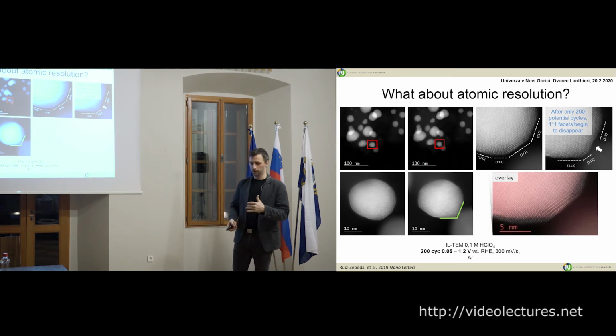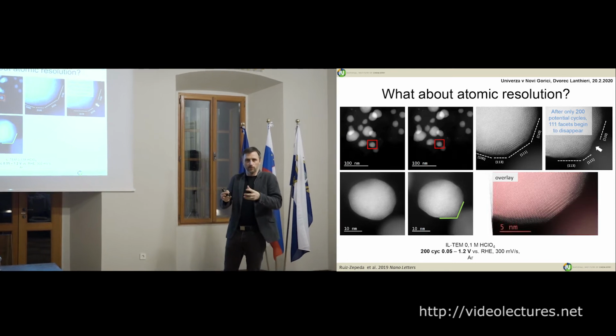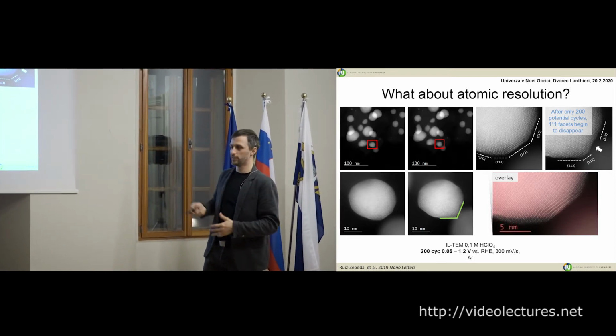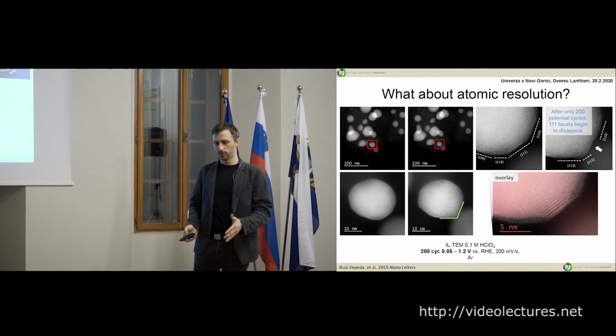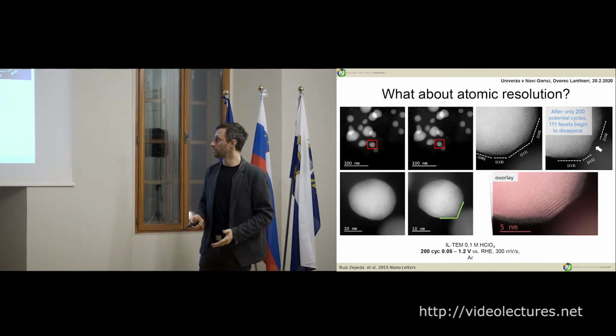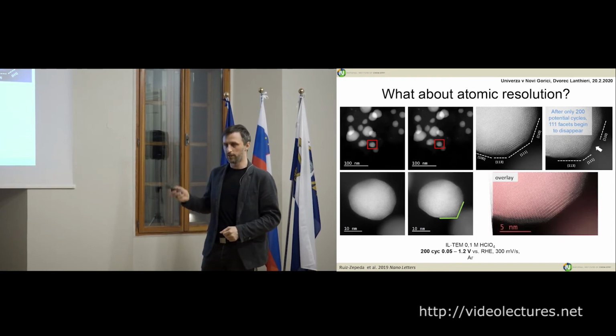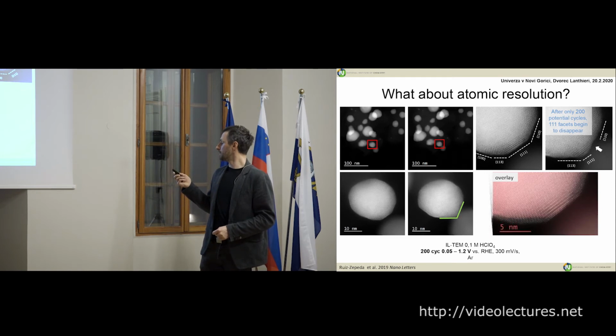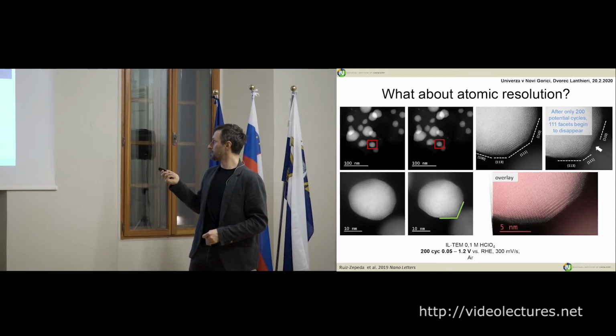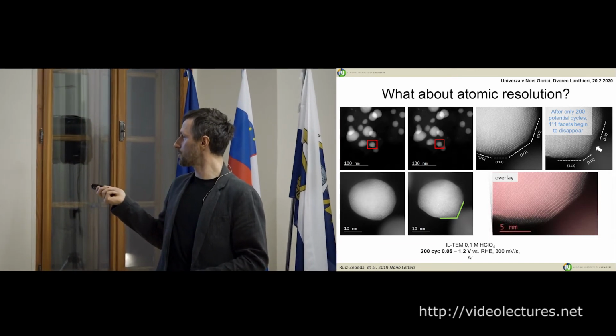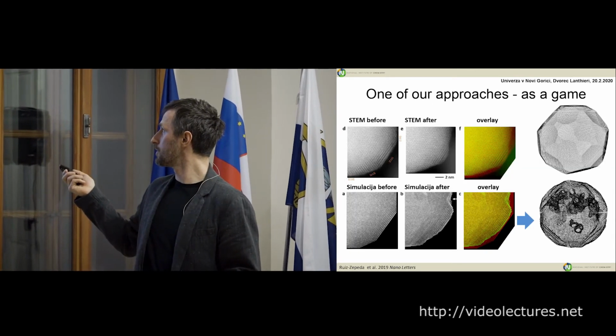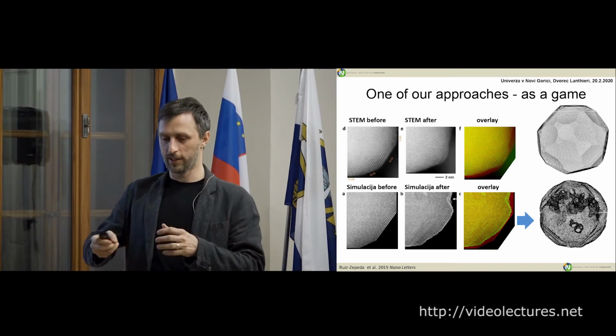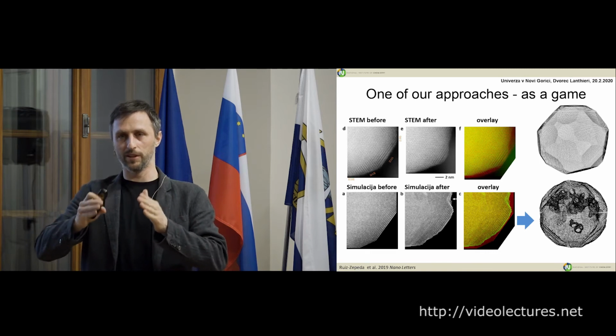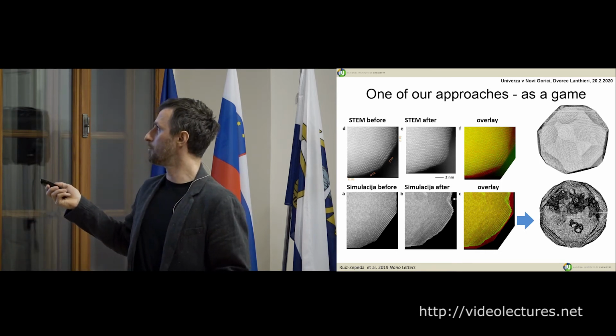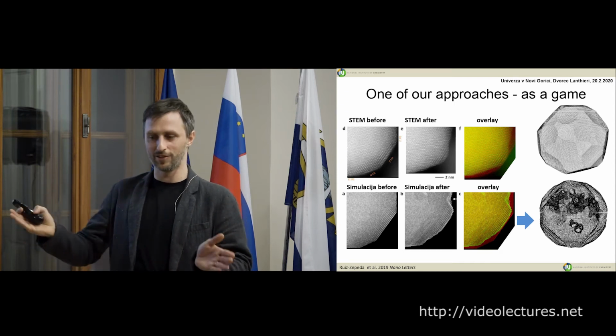And this is peculiar because the 111 facet is the facet with the highest coordination number on the surface, so it should be the most stable one. So why is it then the least stable? And it's also very important because it's usually the most active facet on the catalyst, at least for the fuel cell oxygen reduction reaction. And in this case, what we figured out is that if you overlay these two images, you can see that actually these neighboring facets are getting removed. And just like sharpening a pencil, you're shrinking the 111 facet. So the 111 facet is actually the most stable one, but it's these weak facets that are shrinking it.